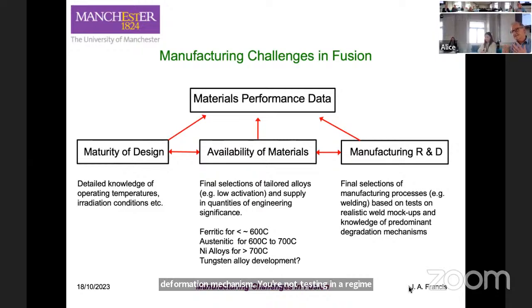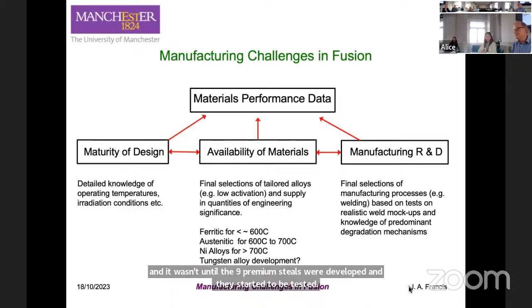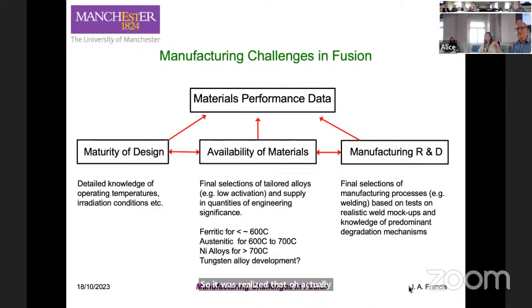It wasn't until the 9 chromium steels were developed and they started to be tested that it was realized that there's one particular zone in the weld that's prone to premature failure in creep. It's heated to between 900 and 1,000 degrees C. Now, in a weld, you've got all possible permutations. Whatever peak temperature you think about, it exists somewhere in the weld, unless you're dealing with a solid state joining process that doesn't heat up.